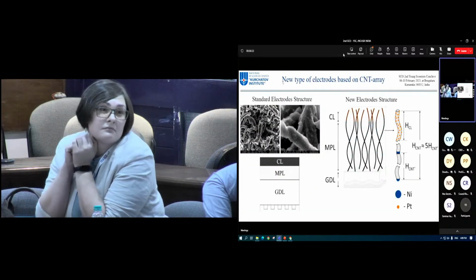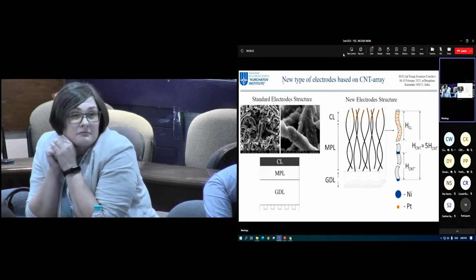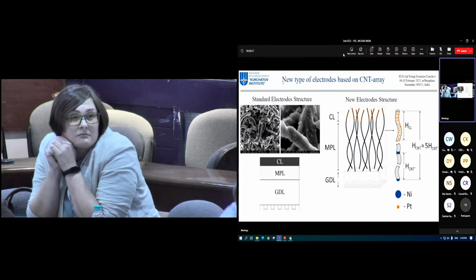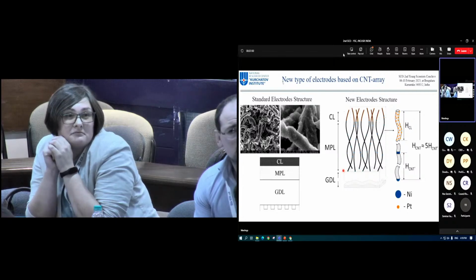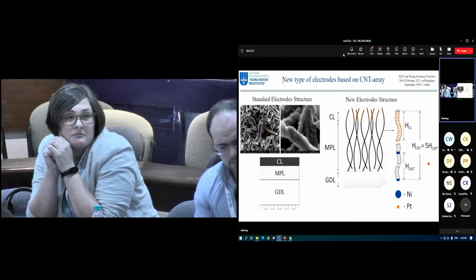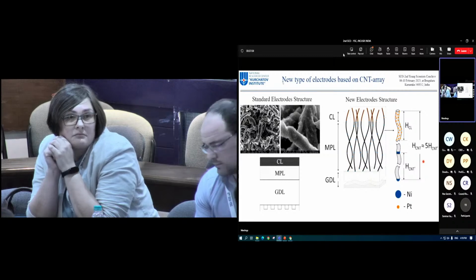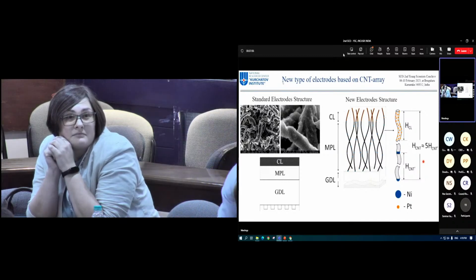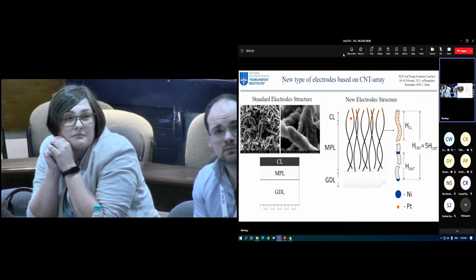The dispersion of catalysts and the method of application lead to the destruction of the structure of the tubes and the low efficiency of the catalytic layer based on them. In this regard, it's interesting to form a new type of electrode, as a complicated system consisting of a gas distribution layer, microporous layer, and catalytic layer, using complex carbon structures, nanotubes, as you can see in the figure.